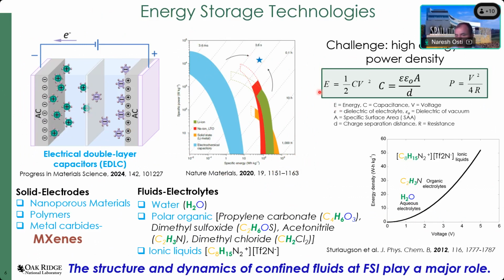If you look at this equation, the energy is a function of the capacitance and the voltage. Capacitance is a property of the electrode material, and the voltage is a property of the electrolyte material. That's why people try to use different types of electrode materials and different types of electrolyte materials. In today's presentation, I'll be focusing mostly on aqueous electrolytes and some organic electrolytes and ionic liquids. The electrode material would mostly be MXenes. And our approach would be to look at the interface, the structure and dynamics of the electrolyte on the surface in contact with the MXene electrode.